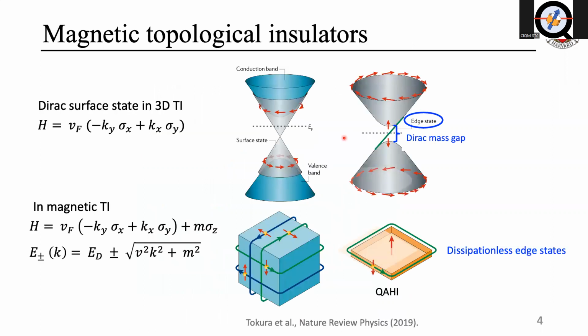Okay. The magnetic topological insulator is one of the best platforms for hosting the quantum anomalous Hall effect. And let's start with a common topological insulator. In a common topological insulator, the Dirac surface state, presented as illustrated here by this k-space and real space illustration, does not have a gap. However, when we have magnetism, the exchange interaction between the Dirac surface state and the magnetism can open up a gap, and this gap is called a Dirac mass gap. And accompanying this, there will be a dissipationless edge state, called the quantum anomalous Hall edge state, and that is what we are dreaming about, to utilize this edge state in electronic devices.